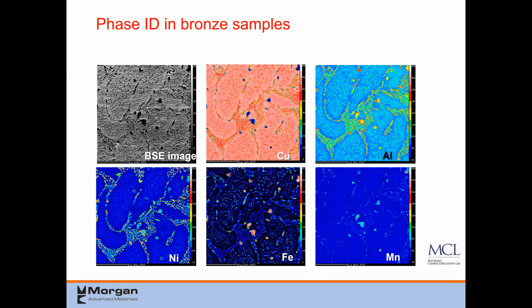And when you're looking at mapping, red means very high concentration, blue is very low concentration. So you can see in this, obviously copper is going to be really strong, but the nickel and the iron and the aluminum show very clearly where the different phases are in the bronze material.